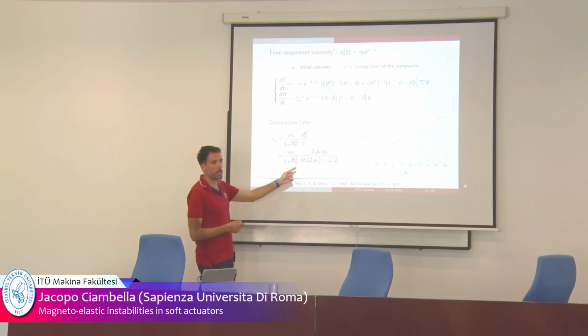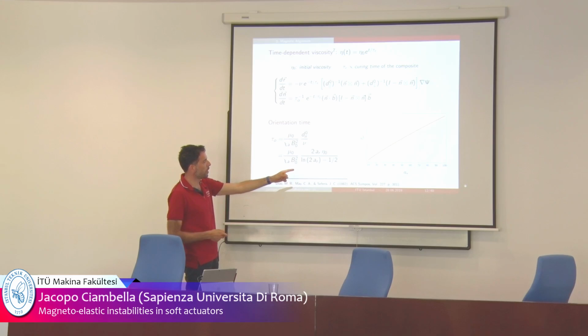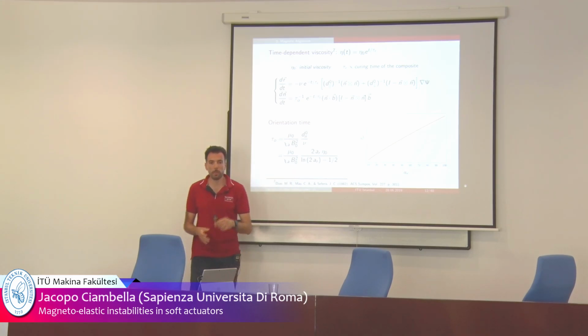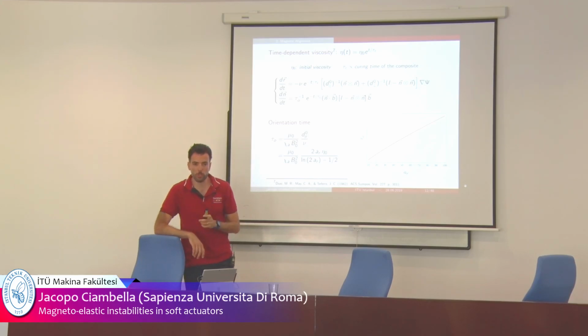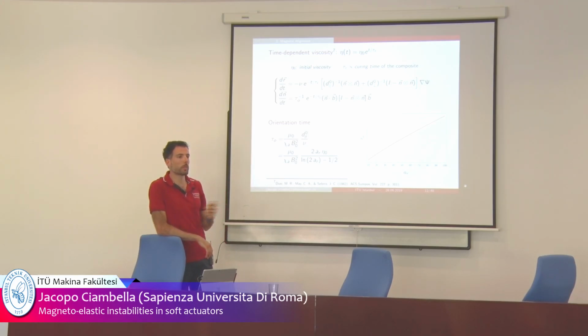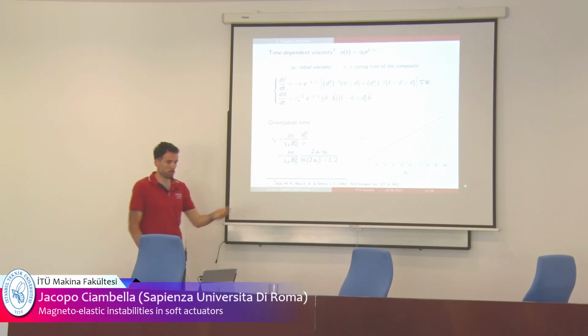The expression is here in closed form, but I plotted it in terms of the aspect ratio of the particle. So what is happening is that if you increase the aspect ratio, the orientation time of the particle is increasing. For a given magnetic field, B0, a longer particle will take more time to orient with the field, with this relationship.